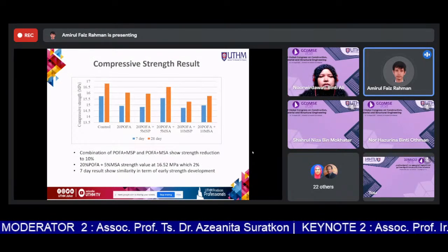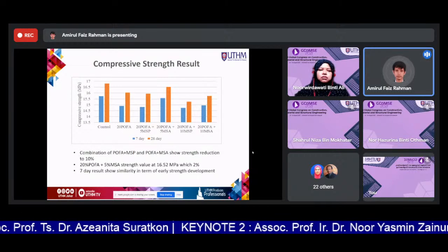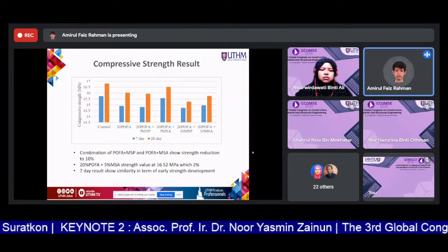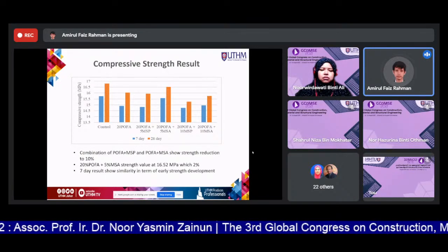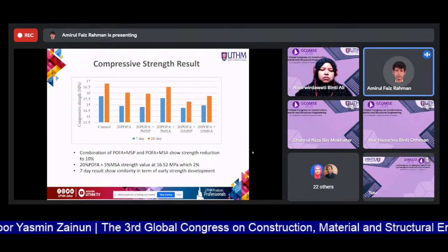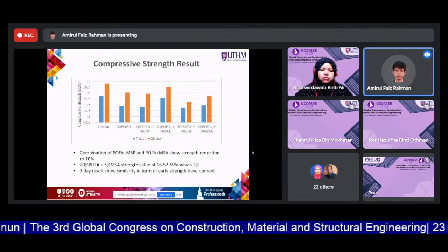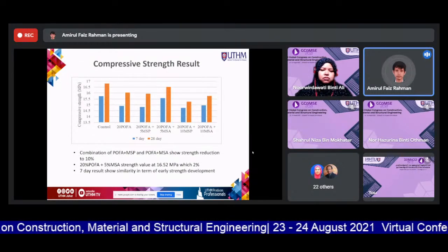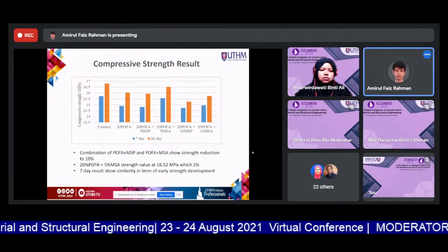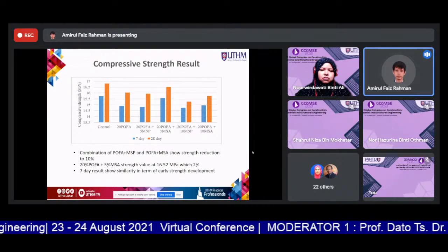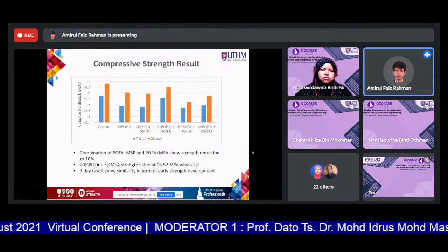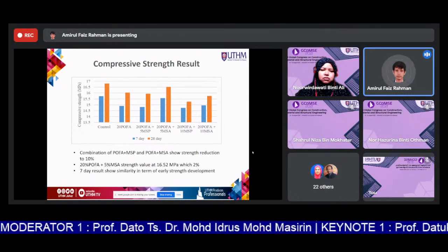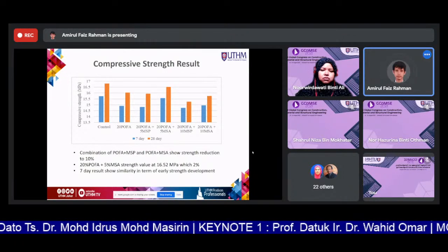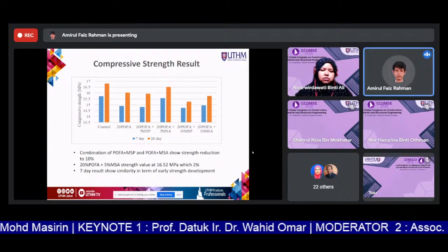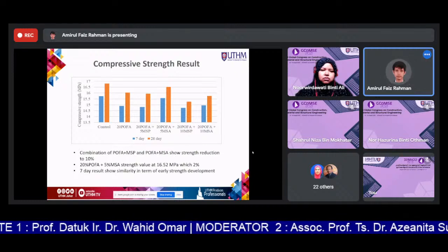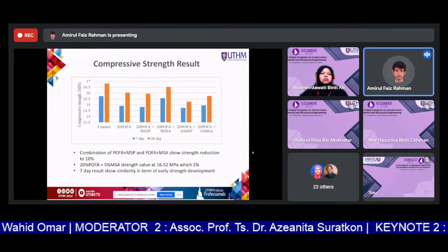And next, for the compressive strength, the trend shows a reduction in all mixtures. In terms of 20% POFA without the addition of mussel shell, the reduction is 16%, followed by 20% POFA and 5% MSA, mussel shell ash. When the total percentage of replacement materials goes up to 30%, which is 20% POFA and 10% mussel shell, the compressive strength result will reduce further. And we can see that there are differences in strength value between the mussel shell powder, which is not burnt, and the mussel shell ash.